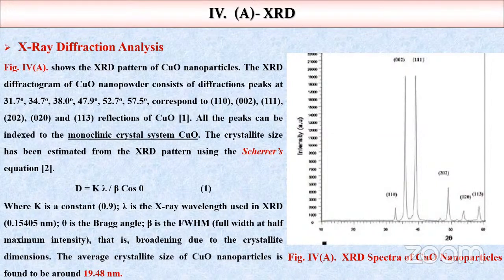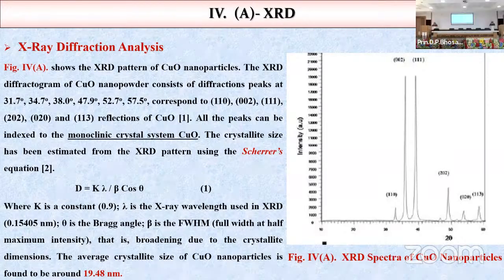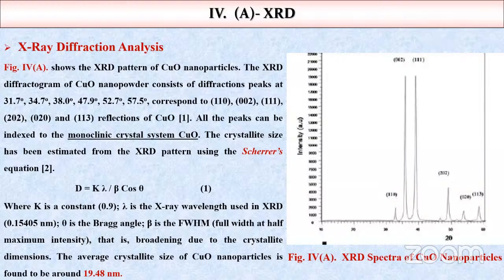The crystallite size has been estimated from the XRD pattern using Scherrer's equation, and the equation is this, where K is the constant and lambda is the X-ray wavelength used in XRD. Theta is the Bragg's angle, and beta is the full width at half maximum intensity, that is the broadening due to the crystallite dimension. The average crystallite size of the copper oxide nanoparticle is found to be around 19.48 nanometer.